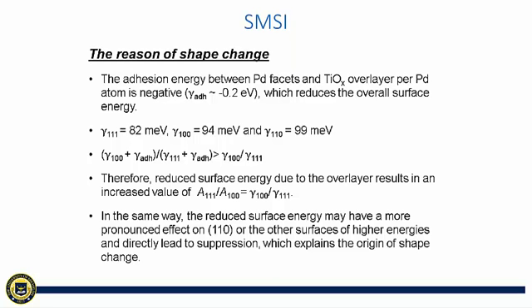If every facet is reduced by the same amount of surface energy, the one with the lowest surface energy initially will become even more favorable. For example, if we have 4 and 2 and both are subtracted by 1, then the ratio will increase from 2 to 3. In a similar way, the reduced surface energy results in the expansion of the 111 plane, shrinking of the 100 plane, and eventually disappearance of 110 and other high index facets.